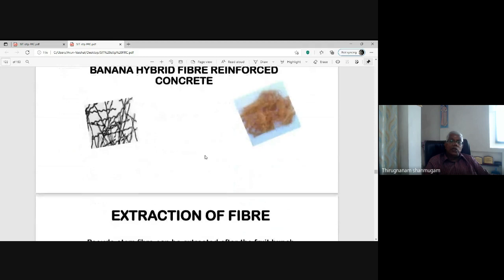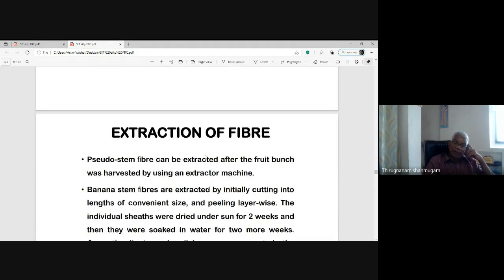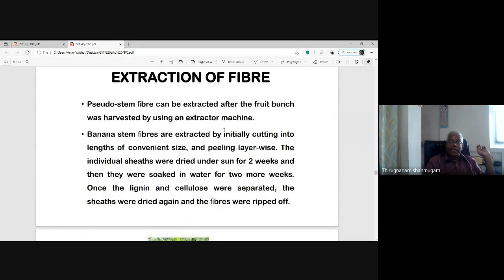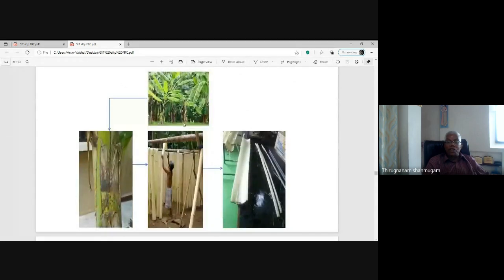Another investigation using natural fibers and vegetable fibers, that is banana fibers. Pseudostem fiber can be extracted after the fruit bunch was harvested by using an extractor machine. Banana stem fibers are extracted by initially cutting into lengths of convenient size and peeling layer wise. The individual sheaths were dried under the sun for 2 weeks and then soaked in water for two more weeks. Once the lignin and cellulose were separated, the fibers were dried again and the fibers were retrieved. That is the sequential operation.